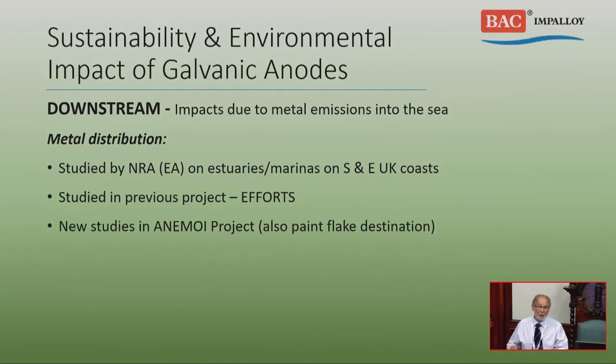They determined that zinc, yes, does go into the water from anodes. It collects more in the sediment than in the water. And that's a feature which has also been determined by the Dutch authorities when they were looking at sources of zinc and cadmium in their drinking water.